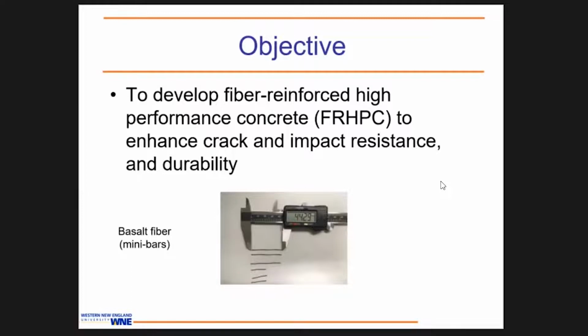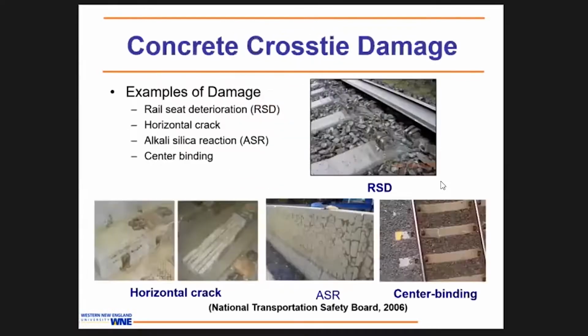From the high-performance concrete domain, earthquakes and elsewhere, they already concluded that if you have low strength or minimum strength concrete, let's use longer fibers because the bonding can be an issue. But if you have high-performance or ultra high-performance concrete, it tends to use shorter fibers because the bond strength is high enough. We would like to see whether that's the case for our concrete as well.